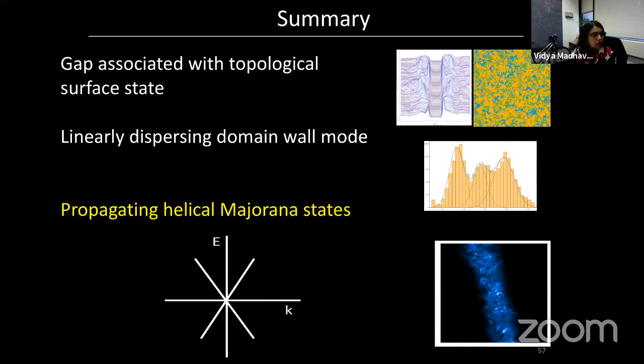About the first question, I'd just like to remind you that this is all happening right at the surface, because the material has surface states, and it's the surface states that are getting gapped out. And it's those surface states that are responsible for these propagating Majorana fermions. So everything's happening at the surface, even though the domain wall itself, we don't know how deep it goes, but at the surface, you have these propagating two-dimensional surface states, which are responding to the presence of the domain wall by creating these Majorana fermions.